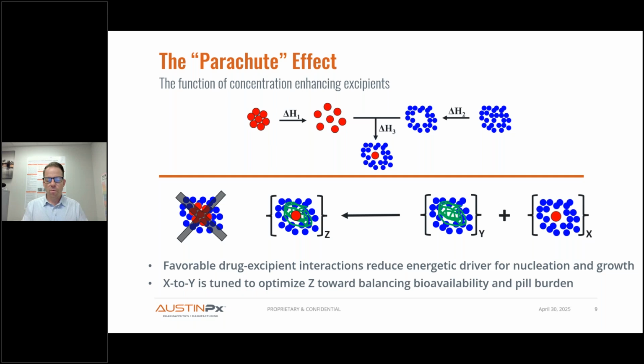So now you've formulated an insoluble drug substance in such a way that it's able to supersaturate, but instead of the drug being naked in solution, you've got excipient materials that can interact with the drug and prevent it from nucleating and growing. And so, pictorially, we're representing that. Favorable drug excipient interactions reduce the energetic barrier towards dissolution and supersaturation, and then reduce the energetic driver to go back the other direction for nucleation and crystal growth. And so at the heart of this presentation is that you want to tune the X, the number of molecules in solution, against Y, the excipient concentration.